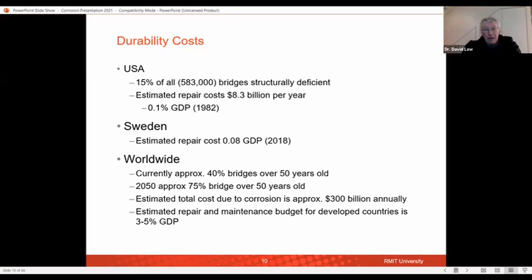So there was a survey going back in the USA, 1982, that identified 15% of all the bridges at that time, which was over 500,000, as structurally deficient. And the estimated repair costs were 8.3 billion a year, equivalent to 0.1% of GDP. And that hasn't really changed much in the last 30 years. There was recently a study done in Sweden, and that estimated the repair costs were 0.08% of GDP.